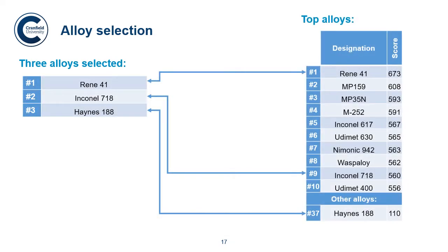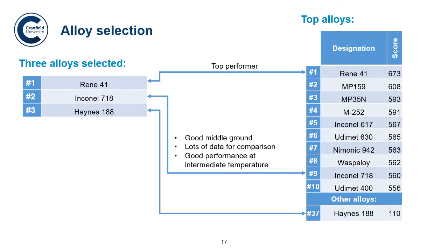So we selected 3 alloys for the continuation of the project. We went with the top performing alloy, Rene 41. We went for 718, which was a good middle ground, lots of data for comparison, and has good performance at the intermediate temperature ranges, as we saw earlier. And then we chose Haynes 188 as it was one of the best performing cobalt based alloys and has high strength at 1500 plus degrees Fahrenheit.